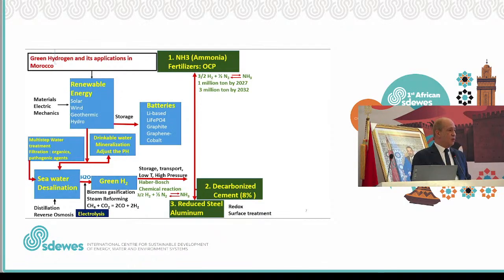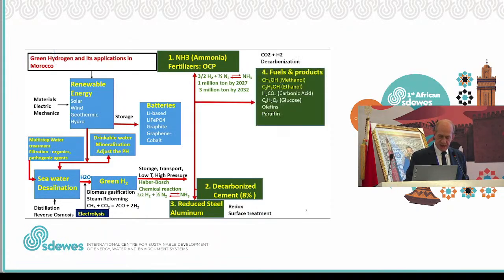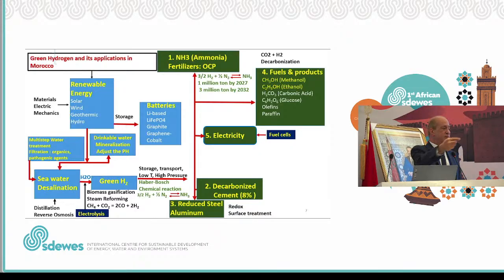Steel is iron. It has either 2 degrees of oxidation, FeO, or 3 degrees of oxidation, Fe2O3. When you have oxygen with iron, the mechanical properties and surface properties are reduced. So you have to remove oxygen. How to remove oxygen? You use hydrogen. Hydrogen plus oxygen, you get water. So to reduce the steel and aluminum industry. The fourth application we are targeting is to generate fuels like methanol and ethanol and other products like olefins. And if you have olefins, you can make a polymerization to obtain polyolefins like polyethylene or polypropylene, and that we don't have. The fifth application is to use green hydrogen to generate electricity, but for that you need fuel cells.